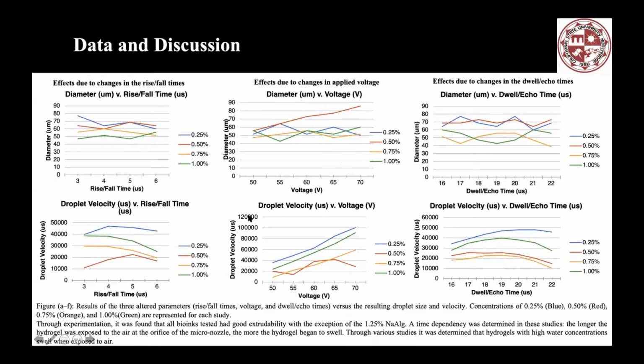Through the experimentation, it was found that all the bio-inks tested have good extrudability, with the exception of 1.25% sodium alginate. A time dependency was determined in these studies: the longer the hydrogel was exposed to the air at the orifice of the micro nozzle, the more the hydrogel began to swell. Through the various studies, it was determined that hydrogels with high water concentration swell when exposed to the air. So this one is still under investigation for further discussion, and for further studies of different mechanical properties in 3D bioprinting in terms of inkjetting technology.